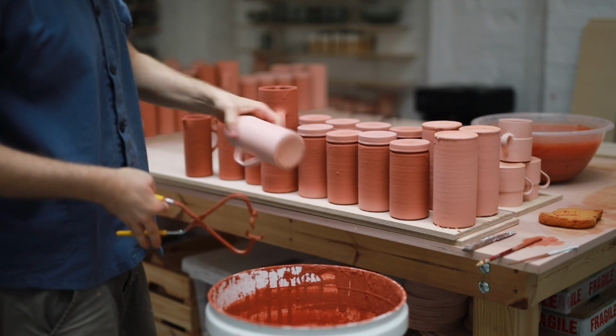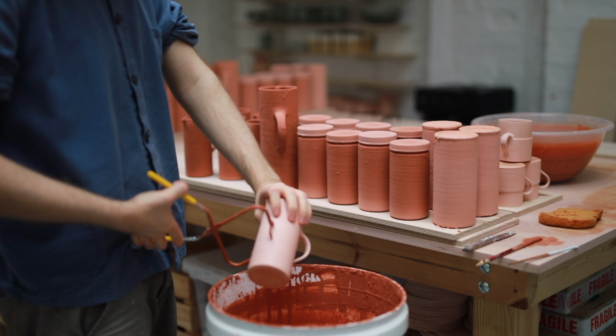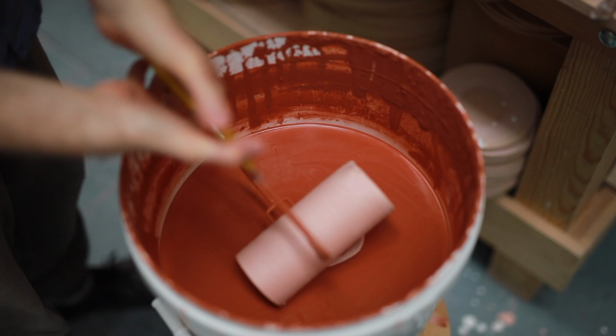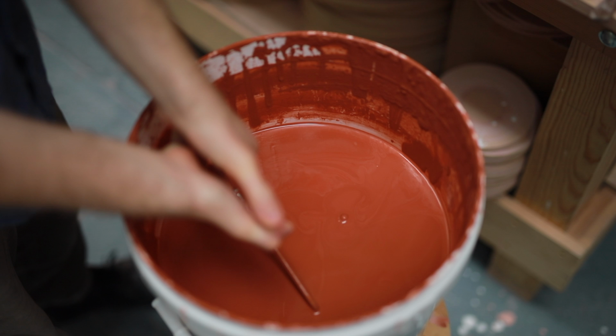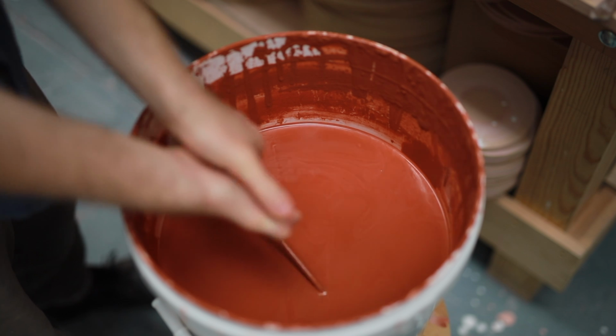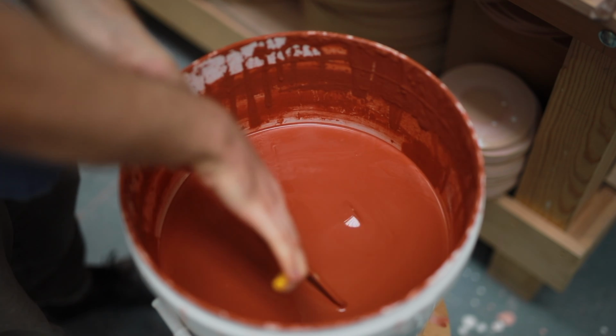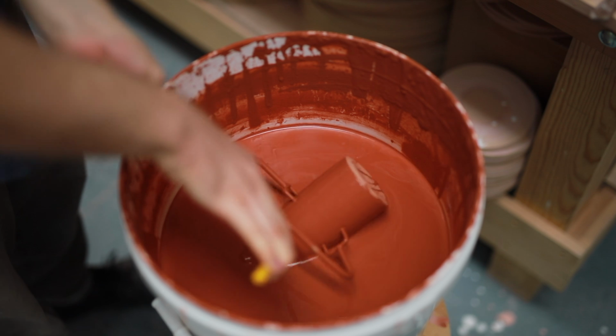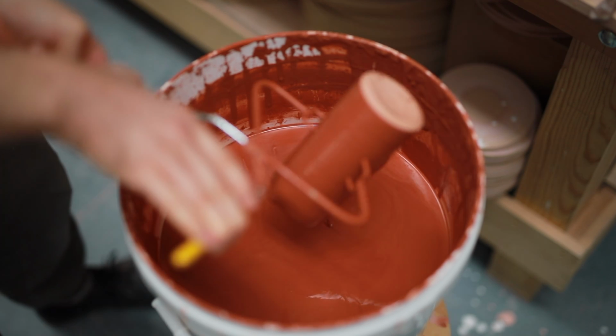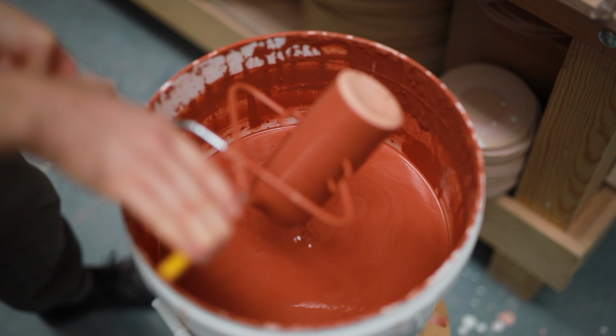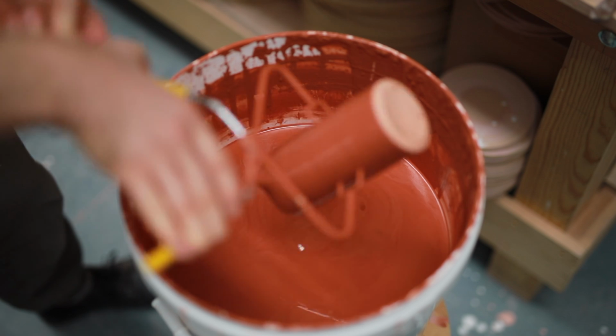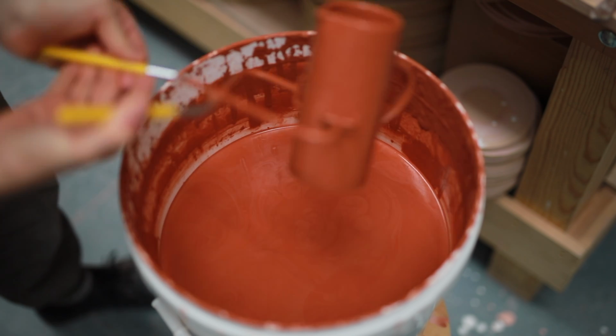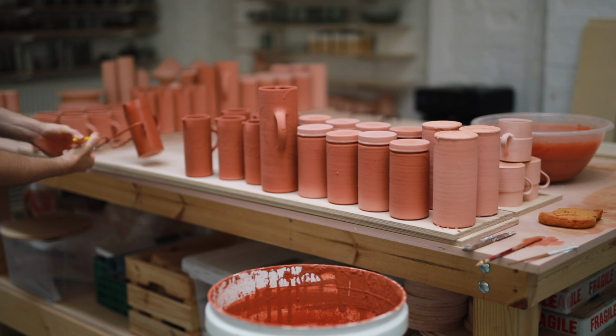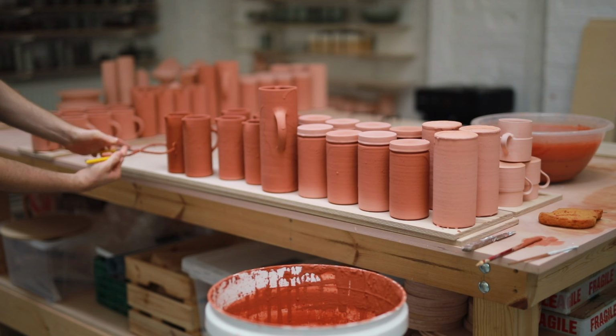The next step is glazing. The pot is delicately grasped between a pair of tongs and submerged into the glaze for a number of seconds. The porous clay body draws in all the water of this solution, leaving just a powdery layer on the outside of all the minerals and oxides and materials of your base glaze. The red colour of this glaze simply comes from red iron oxide mixed into the solution. This here is just 2%, and once reduction fired, this red changes into a deep dark green.